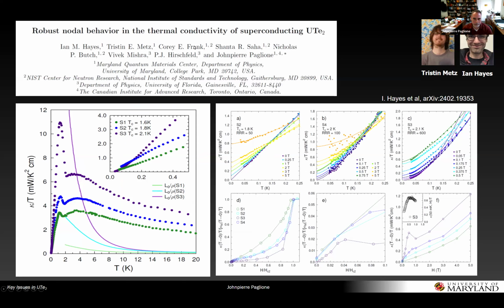First of all, in this paper that we posted, we actually do a comparison from the first generation samples to the intermediate generation, which means TC is higher but still grown by vapor transport, up to the 2.1 Kelvin TC samples. And first off the bat, if you look at the zero magnetic field extrapolations of the temperature dependence, they all point to zero. This is consistent with a clean point node system, which is what we said from the beginning, that this zero residual fermionic component is consistent with a point node gap structure.